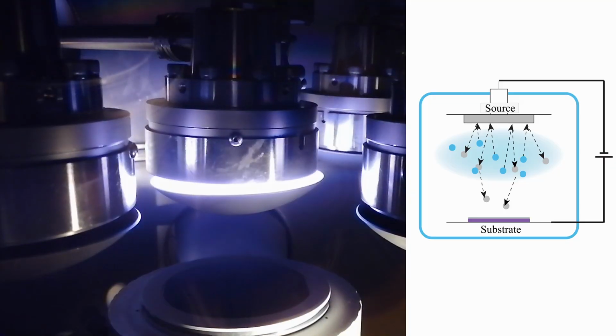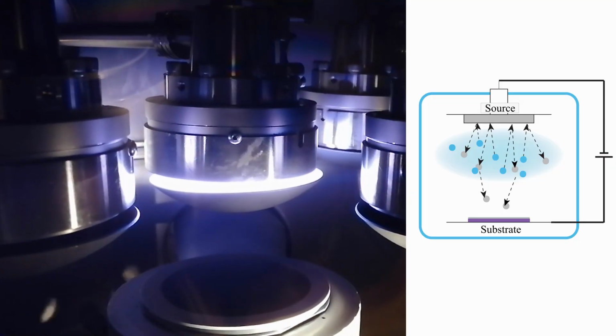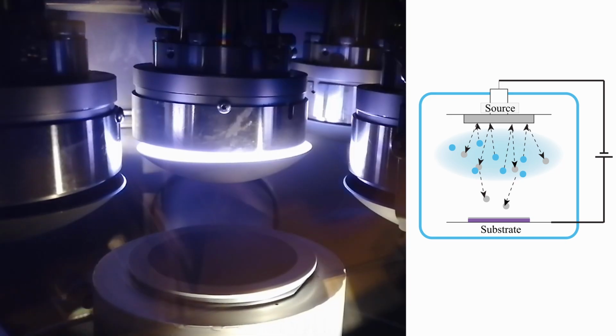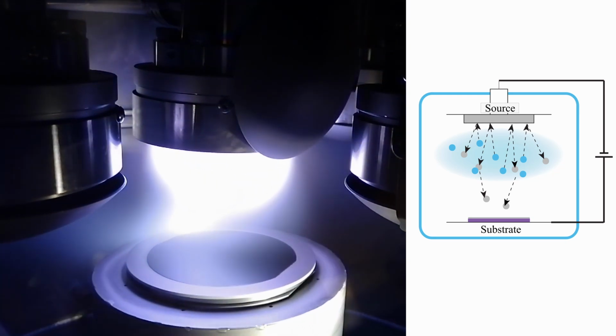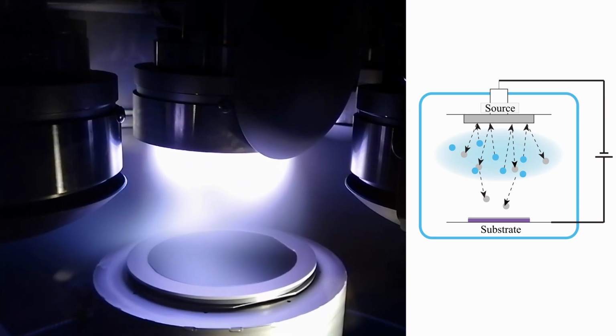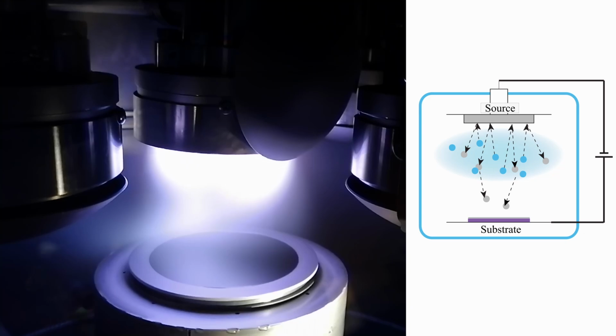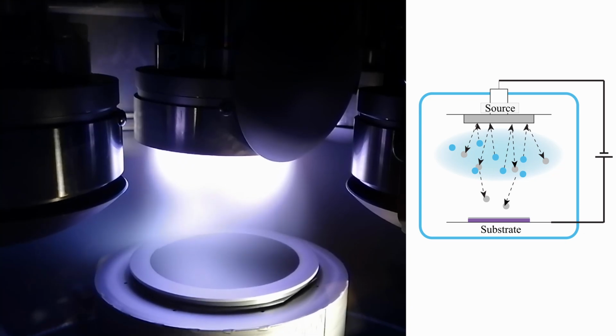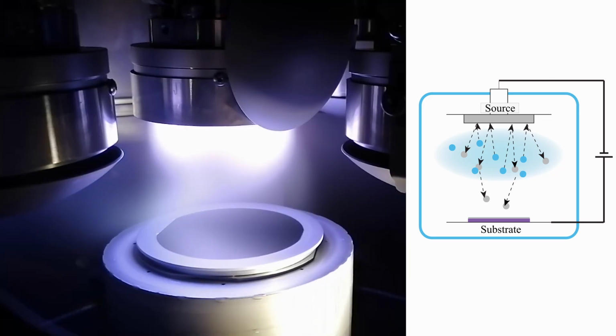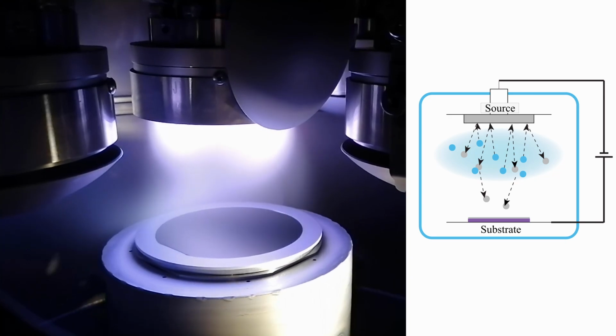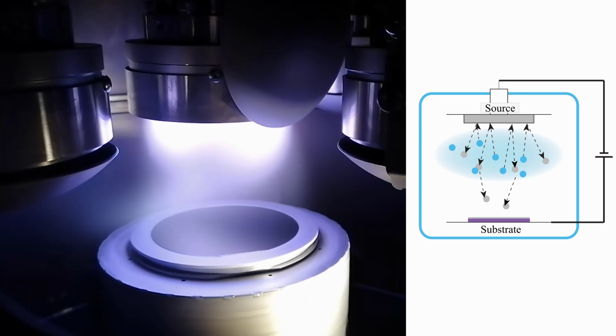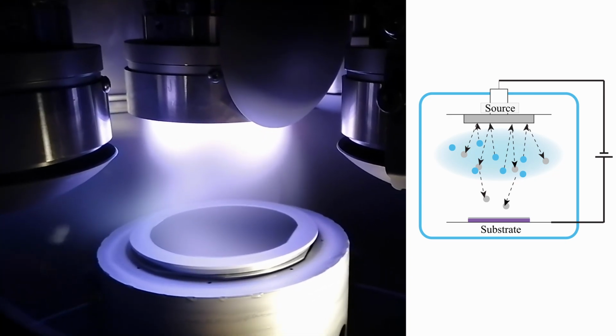Looking inside the deposition chamber, we have the silicon wafer at the bottom of the screen and the source of the aluminium above it. The argon plasma is now ignited, but there is a shutter between the substrate and the source which shields the wafer while the plasma stabilizes and the potentially oxidized or otherwise contaminated top layer of the source is removed. When the shutter is open, the argon plasma, accelerated by a voltage across the source and the substrate, knocks out aluminium atoms from the source, which then land on the wafer, forming a thin metal film.